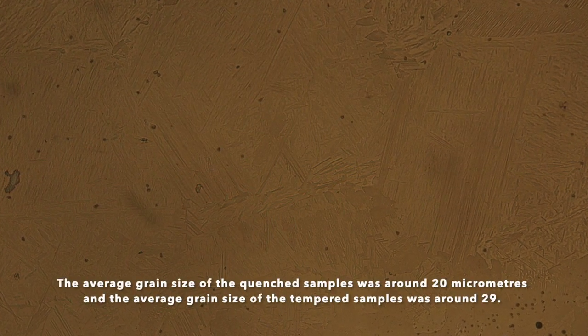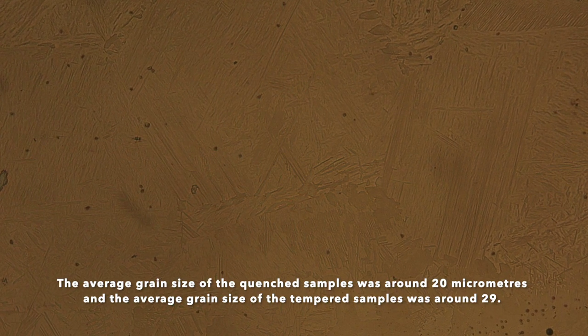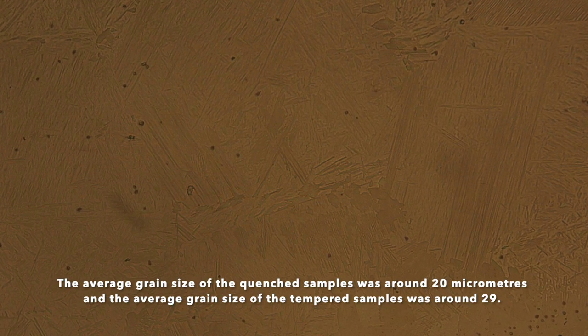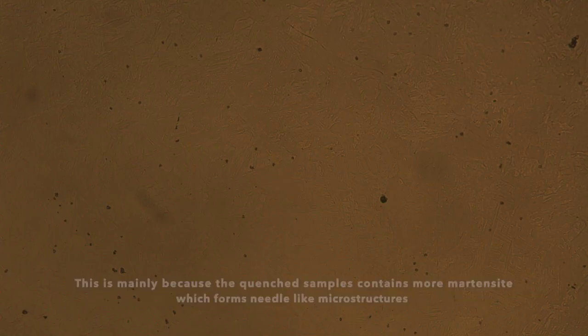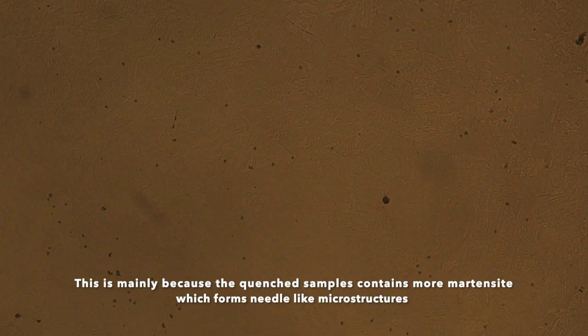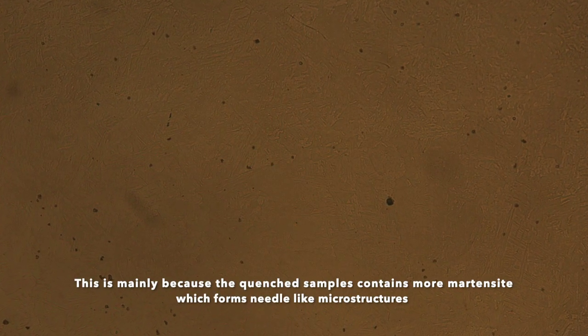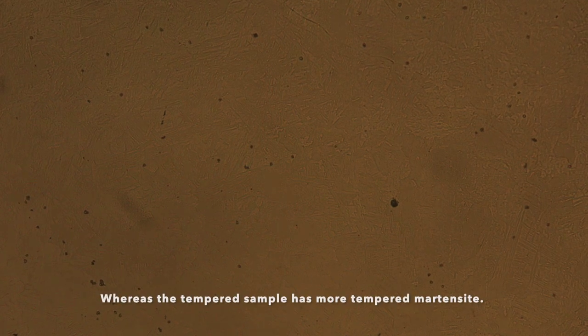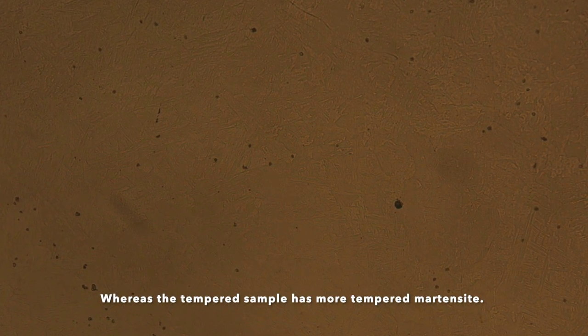The average grain size of the quenched samples was around 20 micrometers, and the average grain size for the tempered samples was around 29. This is mainly because the quenched sample contains more martensite, which forms needle-like microstructures, whereas the tempered sample has more tempered martensite.